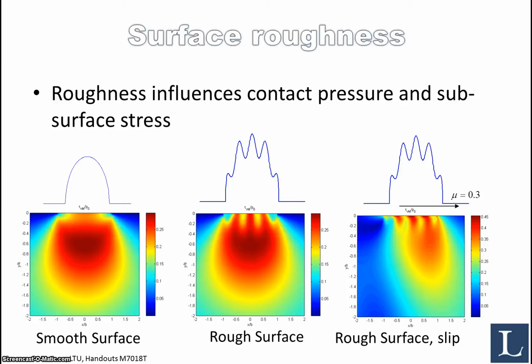And if you also add a slip, meaning that you have some sliding between the components and not just pure rolling, you can then also shift this stress distribution in the subsurface in some direction depending on the direction of motion. So these are important parameters to keep in mind when you, for instance, design bearings or deal with bearing failures, to backtrack what can have caused the failure that you observe.